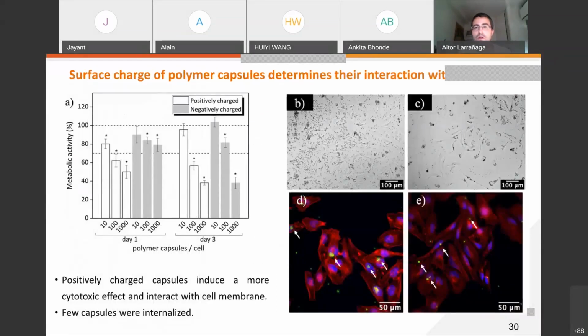And then we proceed with the in vitro characterization of our capsules. And in this case, we use HeLa cells for this in vitro characterization. In this project, we also wanted to study the effect of the surface charge of the polymer capsules in their cytocompatibility and also in their interaction with cells. So for that, we fabricated polymer capsules with either positively or negatively surface charge. And we found quite clear differences between these two kinds of capsules.